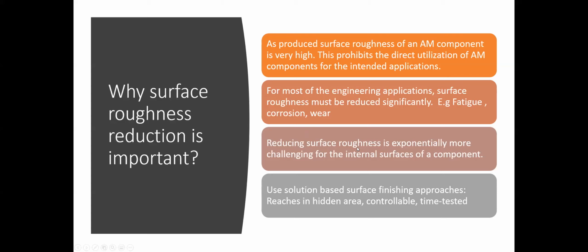The next reason is that reducing surface roughness is exponentially more challenging for the internal surface of a component. Metal 3D printing is touted as important because it can produce very complex geometries which you cannot produce any other way. But when you produce a sample like that, there are a lot of internal surfaces which you cannot clean or reduce the roughness of. Our group has been expert in that area, how to clean inside of complex samples. I would be speaking a little bit about that.